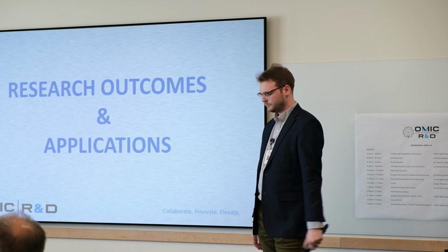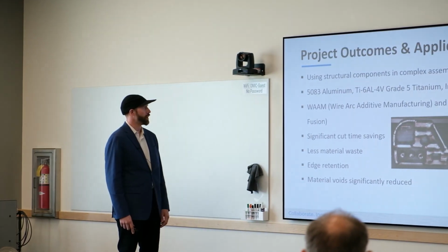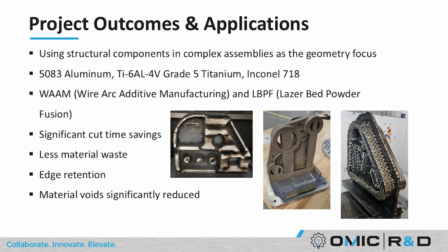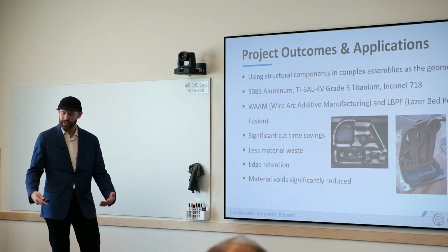And then some of the outcomes and applications of this. Rolling through, we were able to use structural components, part of our design motif. We were able to run three different structural alloys and use two different print strategies. We were significantly cutting time from cutting these out of just block, plate, what have you. We definitely reduced material. You look at a bucket of chips after hogging any of these out of billet, we barely used a quarter of a 55-gallon drum when machining any of these. So it's very, very economical from a material-based standpoint.